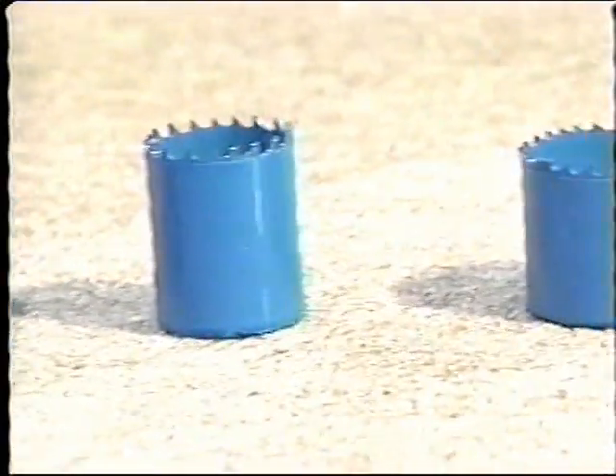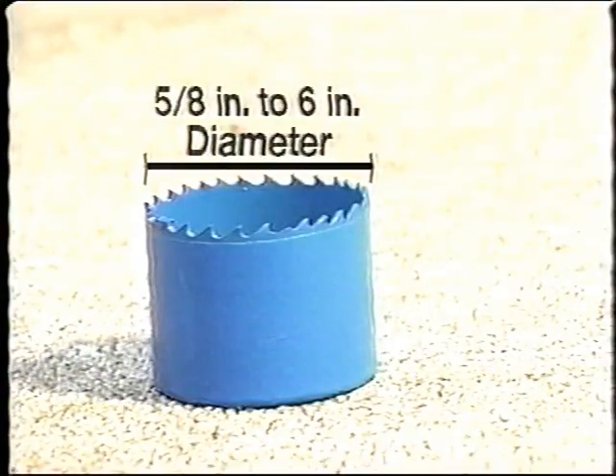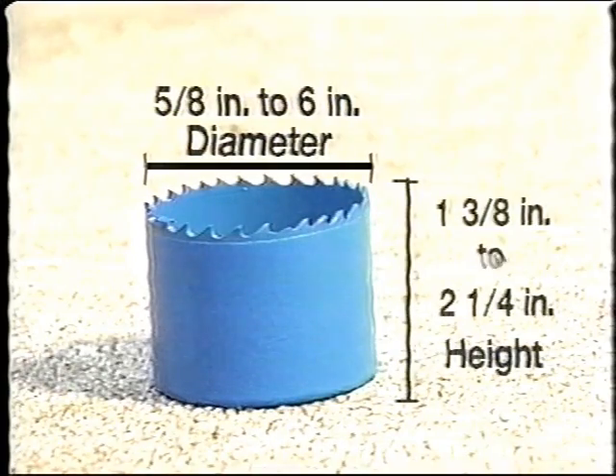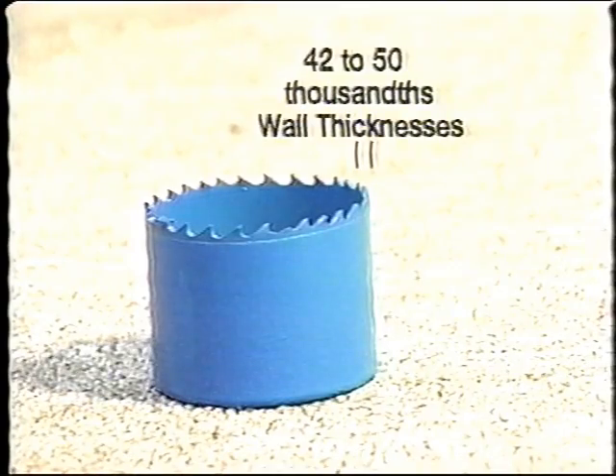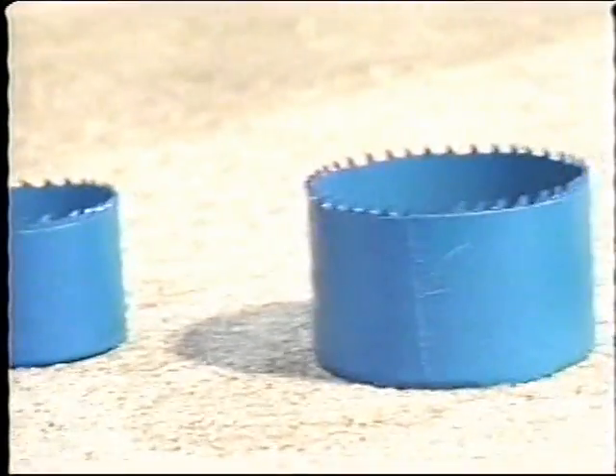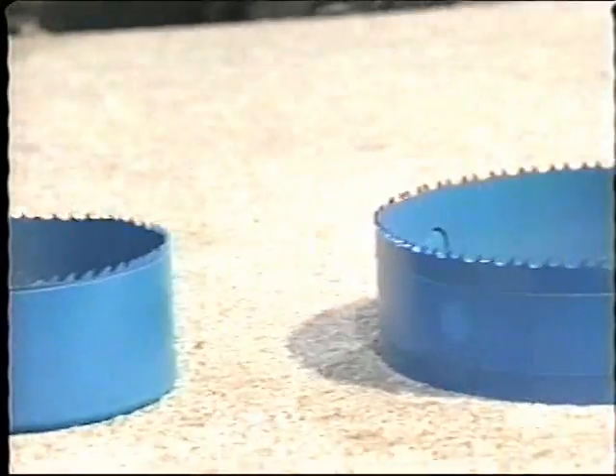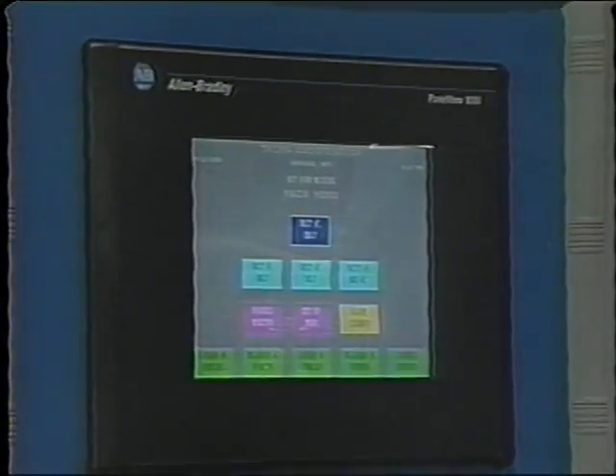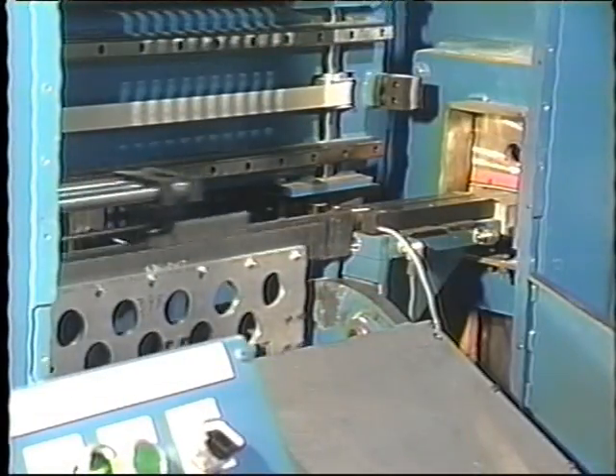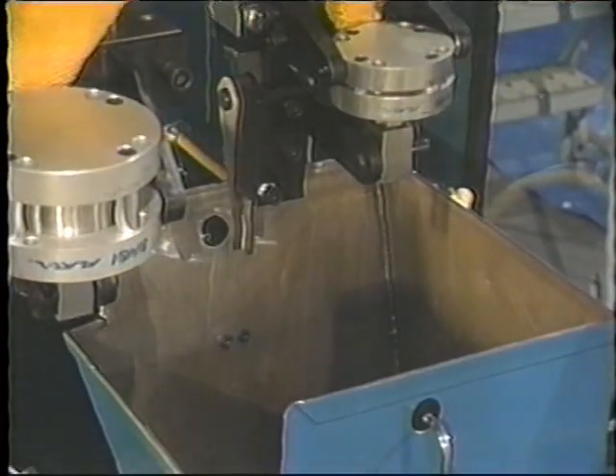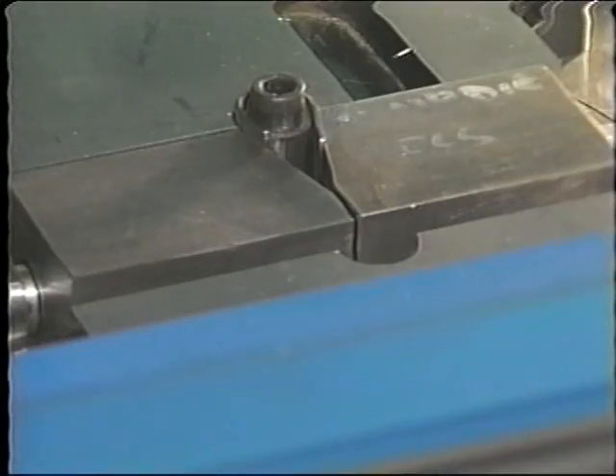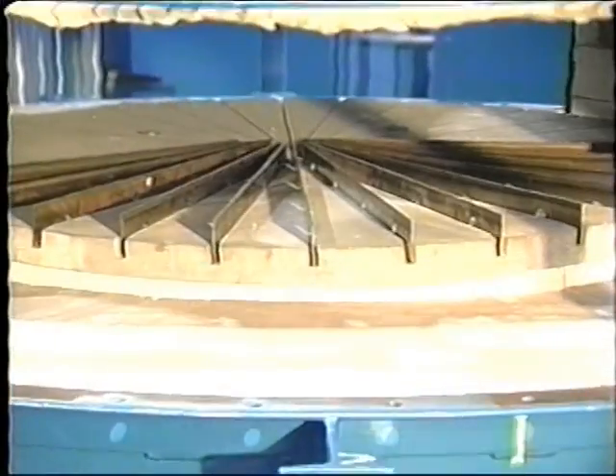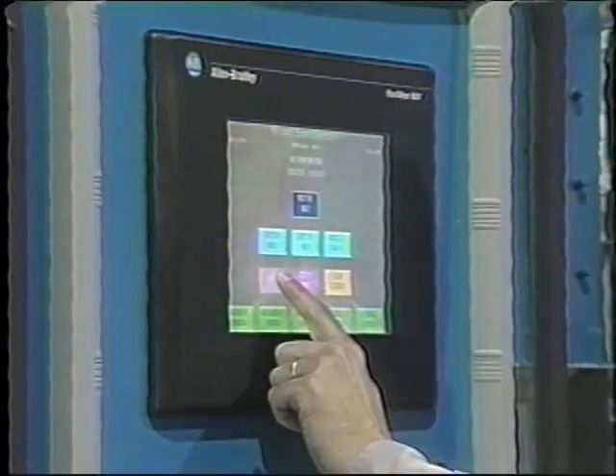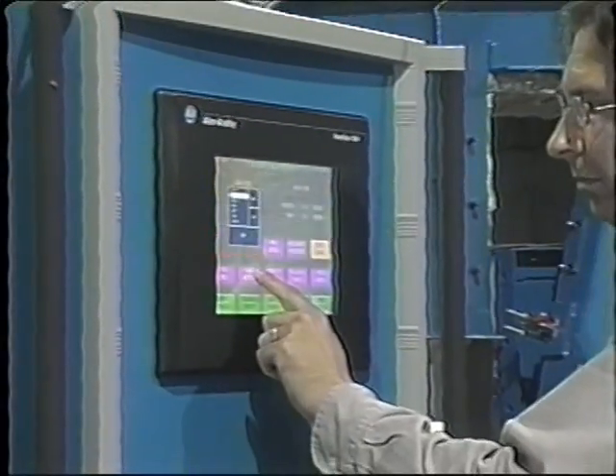All our standard systems will produce hole saws 5/8 inch through 6 inches diameter, heights from 1 3/8 inch through 2 1/4 inches, and thicknesses from 42 to 50 thousandths. Other sizes can be accommodated with modifications. The cycle time is adjustable from the operator interface panel. Average cycle time of the system is 12 seconds, thus producing 5 hole saws per minute per line. This is based on a 4-second quench time in the forming dies and a 2-minute soak time in the furnace. Changing quench times or soak time will directly affect the cycle time.